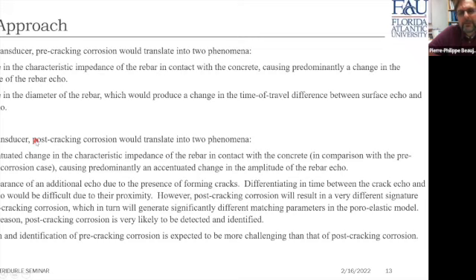Using this transducer, post-cracking corrosion would translate into two phenomena as well: an accentuated change in the characteristic impedance of the rebar in contact with the concrete in comparison with the pre-cracking corrosion case, which in turn would cause predominantly an accentuated change in the amplitude of the rebar echo. The second phenomenon would be that we would observe an additional echo due to the presence of forming cracks. Differentiating in time between the crack echo and rebar echo would be difficult due to their proximity.